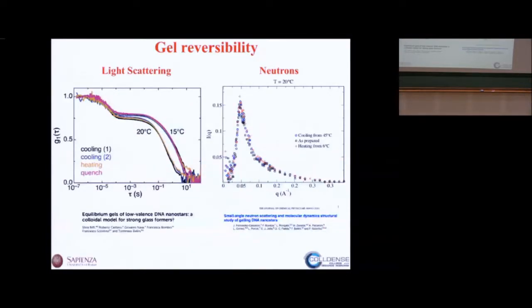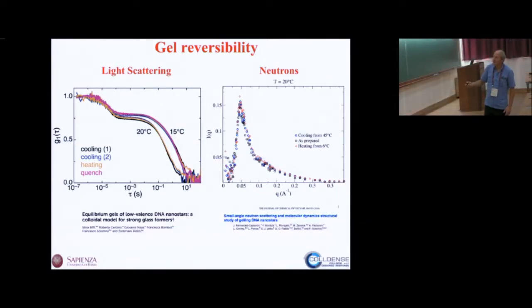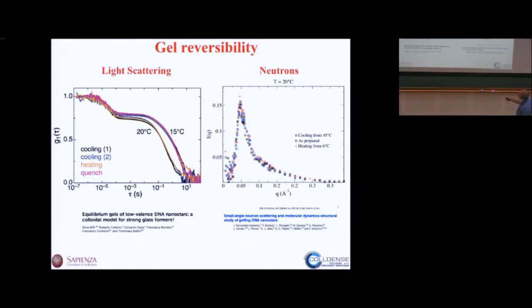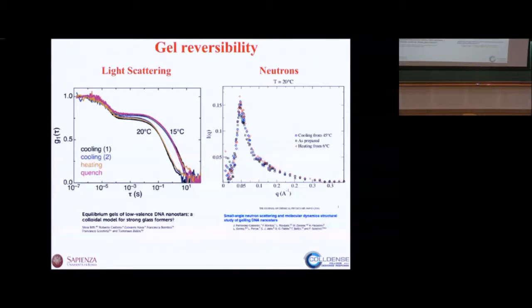These things are really equilibrium gels. I mean, things that you can cycle back and forth in temperature. You always find the same correlation functions. You can go on cooling or on heating. You can quench directly to the temperature. They're really equilibrium structures. You wait 30 minutes, and then the system always goes to the same configuration, with the same resulting correlation function, the same scattering profile. So it's really an equilibrium system.